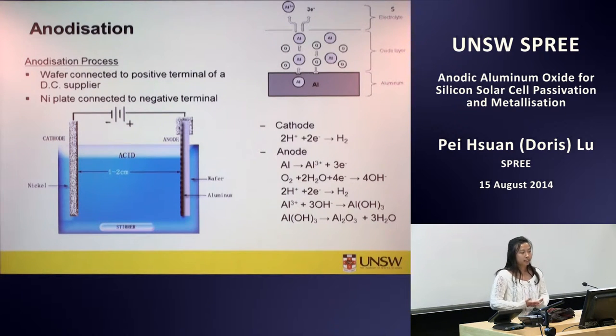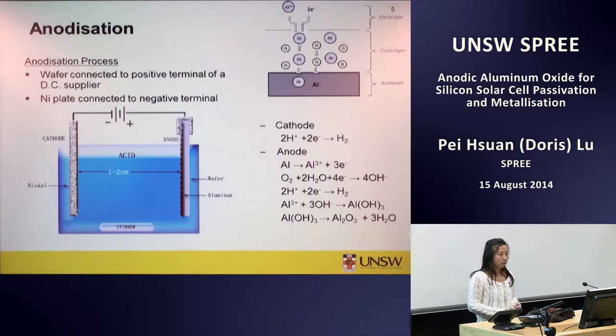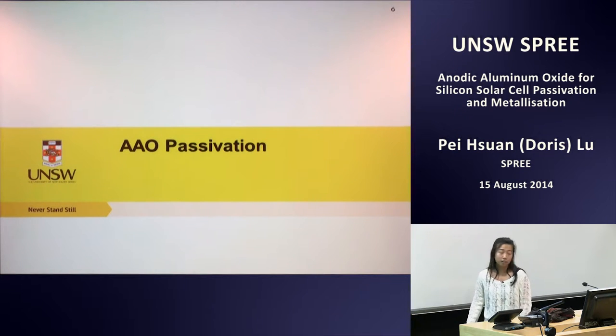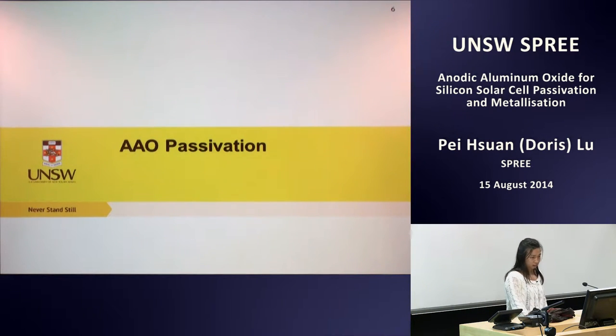works. Once you apply the external electric field, the aluminium starts losing electrons and forming aluminium ions. The external electric field drives the aluminium ions and hydroxy ions to react to form aluminium hydroxide. And with time, aluminium hydroxide will dehydrate and become aluminium oxide. This formation gives the anodic aluminium oxide film a high concentration of hydrogen and stored charge, which could possibly be used for passivation on silicon solar cell.